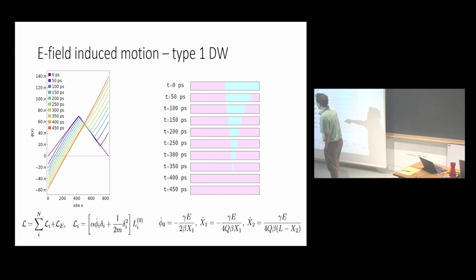And as I'm running the simulation, I see that, so plots are done in equidistant time increments, this wall is moving really fast, right? So here the curves are all close, but this wall is moving very fast because its velocity is basically 1 over domain wall width. So in the numerical spin dynamics simulations, we are confirming the analytical argument from before that the velocity is inversely proportional to domain width.